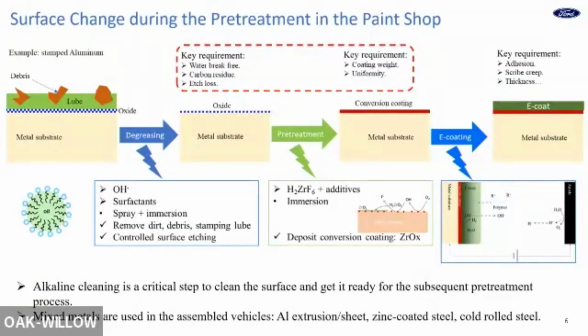The purpose of this process is to remove the dirt, debris or stamping lubricant, so you can get a clean surface, especially an oil-free surface. Then you may also try to control the etching, so you can etch the surface for the subsequent pre-treatment. Here we are more focused on the thin film or zirconium oxide-based pre-treatment. This is a key chemical, and sometimes you see some additives to either increase the coating formation rate or get a uniform conversion coating deposition.